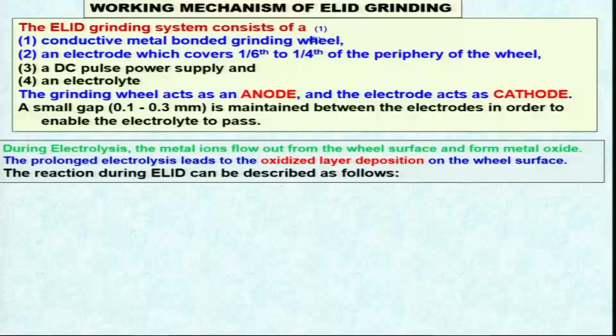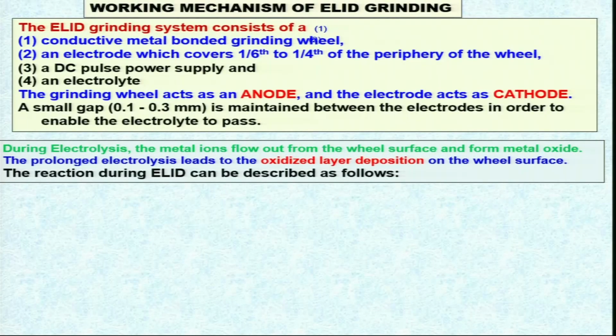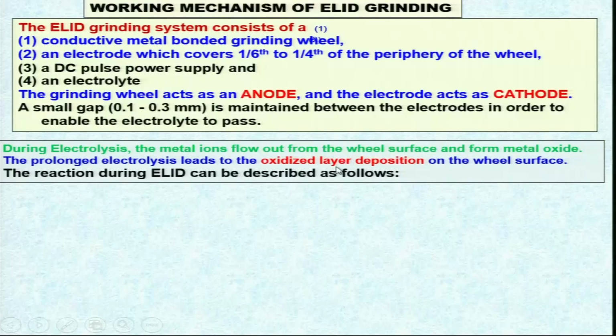During electrolysis, the metal ions flow out from the wheel surface and form oxide, and we have already seen this oxide film, reddish in color, which is being formed. The prolonged electrolysis leads to oxidized layer deposition on the grinding wheel. The reaction during ELID can be described as follows.